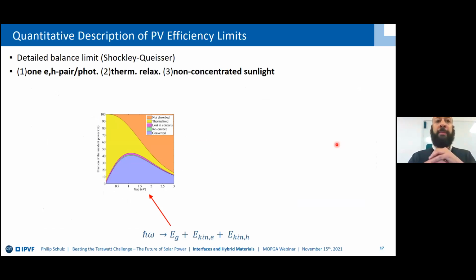And there is, of course, a mathematical description for this. It's called the detailed balance limit after Shockley and Queisser. There are some assumptions, not hyper important here. It's only one electron hole pair, you have thermal relaxation, and it's non-concentrated sunlight. But this plot here is actually quite critical, because for a given material with a specific semiconductor band gap, you look at the fraction of incident power. If you have a high band gap material, this orange part becomes most prevalent, and you can see in the legend it means not absorbed. So this is all light that passes through.